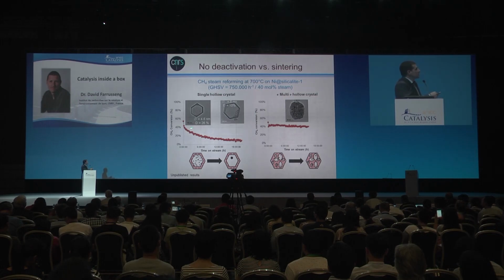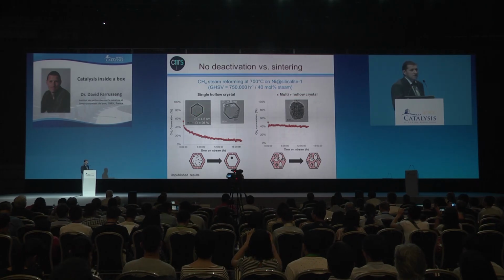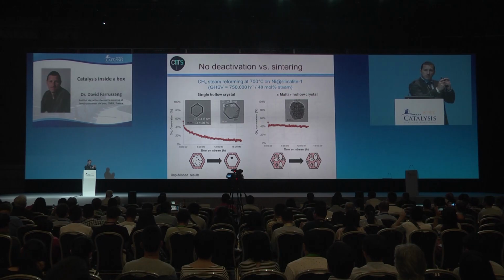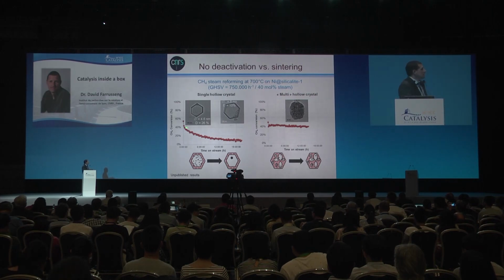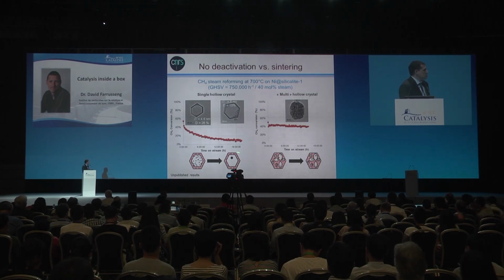In this case, here we have characterized the catalyst. You may see here very small nickel particles. In this case, for the nickel, we don't have a single particle, but many small ones that are attached to the surface. And after a while, they sinter. So you see, you lose a factor of 3 in the dispersion, which corresponds more or less to a factor of 3 in the catalytic activity, which is here.